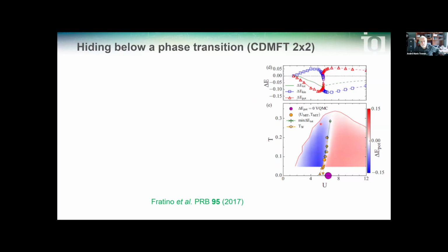And this is an antiferromagnetic phase boundary. Because it is CDMFT, that would be a crossover in a real d equals 2 model, even though the ground state is an antiferromagnetic phase for all values of U less than the Mott transition at that filling. So this is the orange line that corresponds to the normal state, if you want. The antiferromagnetic transition is potential energy driven, while it is kinetic energy driven at large U.